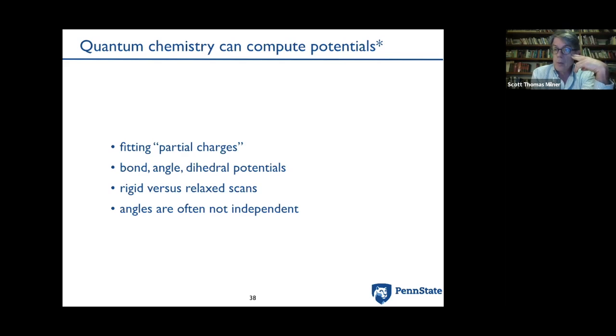Well, one place that they can be got is by calculating, using quantum chemistry packages like Gaussian, a best fit point charge for each atom, and best fit to what? Well, best fit to the electrostatic potential in the vicinity of the molecule, someplace on the space-filling surface, because that's where other molecules can get close to at normal temperatures and pressures.